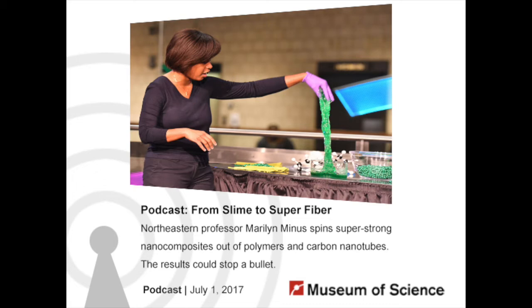One thing that we do in our system is, because polymers don't necessarily like being aligned all the time, they prefer to be more wiggled up or coiled, as we call it, we actually need to keep them aligned. And so we use in our research carbon nanotubes, which prefer to be straight because they're rods, and we put them in there with the polymer. For some reason the polymer likes to act like the nanotube once they're around each other. So the polymer chains that are really close to the nanotubes stay straight. The rest of the polymer chains might wiggle up, but as long as I can get most of them to line up in my fiber, that makes the properties go in the right direction, which is strong for us.